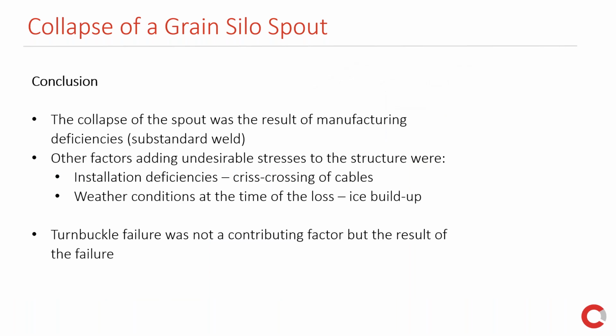Following extensive examination, the conclusion was that the collapse of the spout was the result of manufacturing deficiencies. It was a substandard weld with voids and significant beads. Other factors adding undesirable stresses to the structure were considered: crisscrossing of cables and ice buildup, because the incident occurred in November after rain and ice buildup on the structure. And as I mentioned earlier, the turnbuckle failure was not a contributing factor, but the result of the failure.